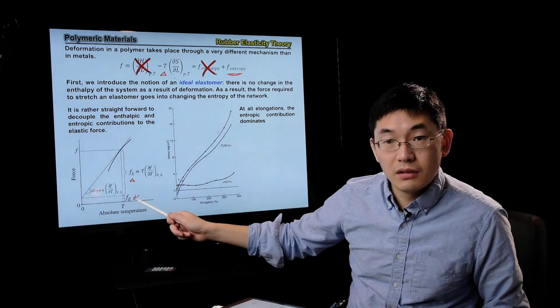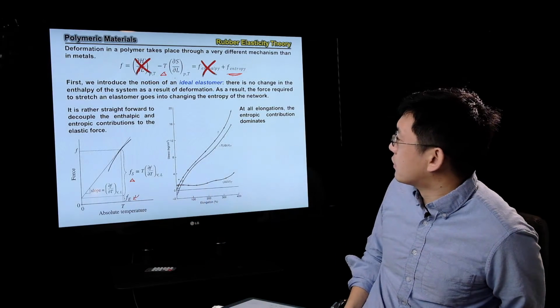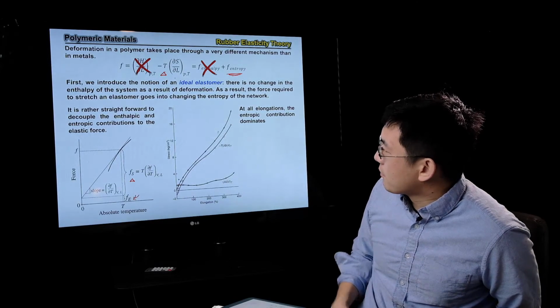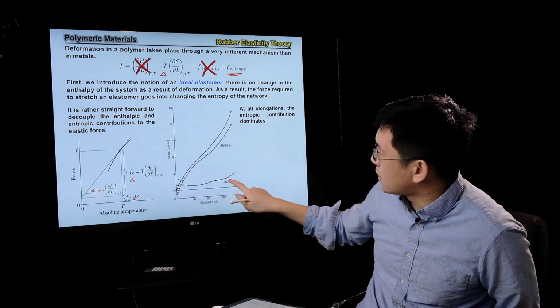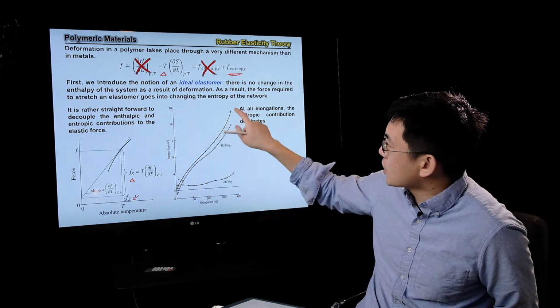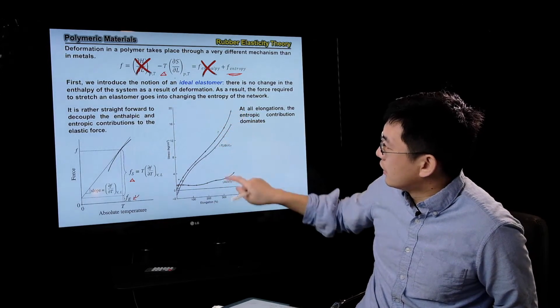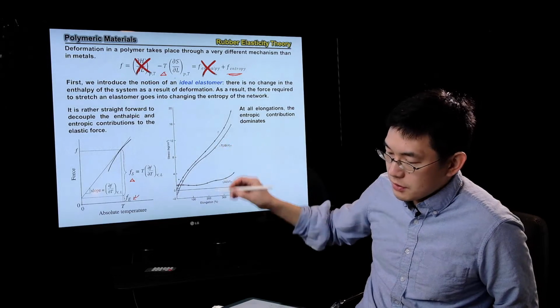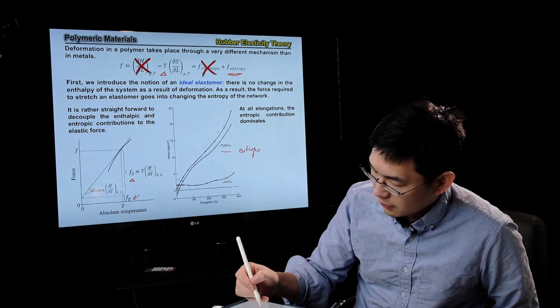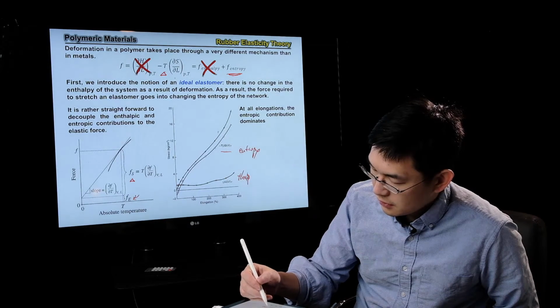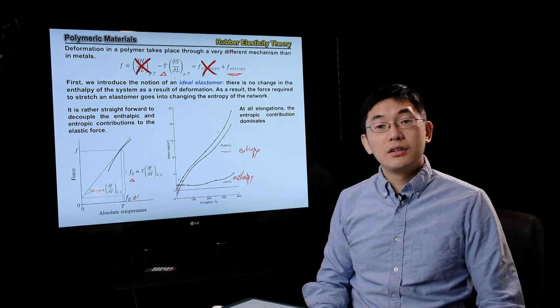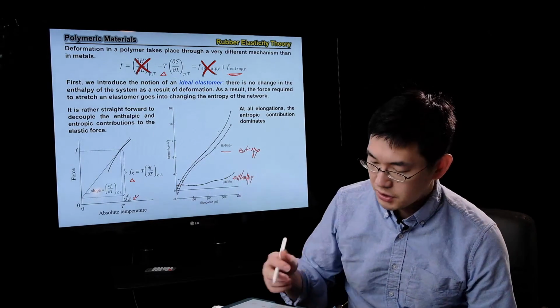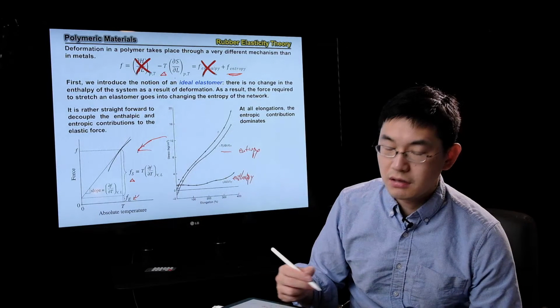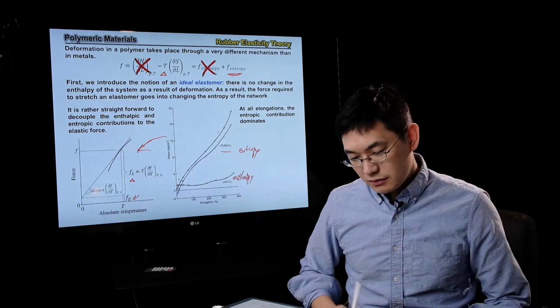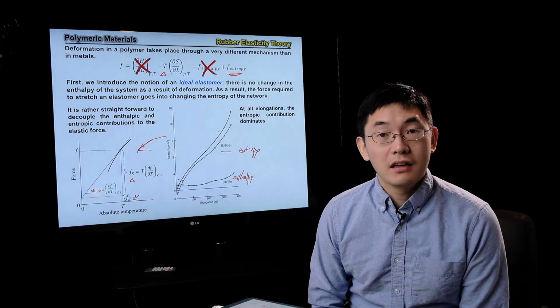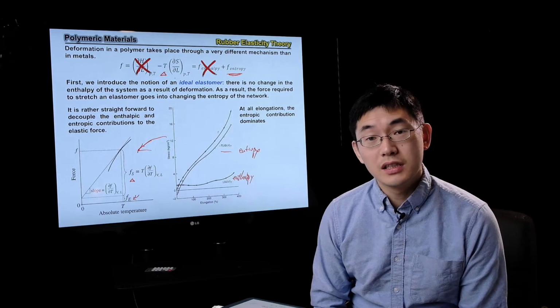This is the theory, or what people expect, and this is what people have actually measured for a real rubbery material. You can measure stress versus elongation, and we can further deconvolute it into contributions. So this is raw data shown as the F curve with crosses here, and they can deconvolute it into the entropy contribution, as shown below. You can tell it's not perfect, but it pretty much agrees with the assumption that energy doesn't play a great role. So I want to stop right here today, and in the next lecture we're going to explore more details.